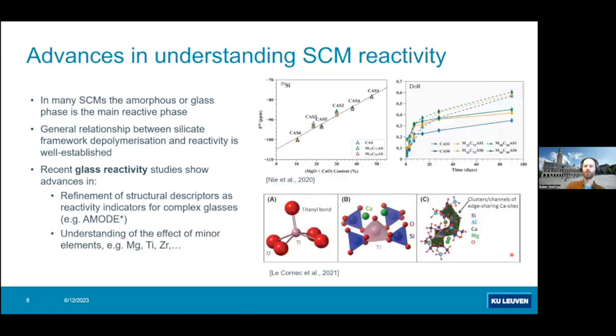Also, the effects of minor elements have been looked into more closely. The effect of titanium as a suppressor of reactivity has been researched in the literature as well. The effect of magnesium, or the magnesium to calcium balance, was investigated by the group of Professor Skibsted, showing that magnesium mainly has a role as a framework depolymerizer, and that any other effects are rather subordinate to that.